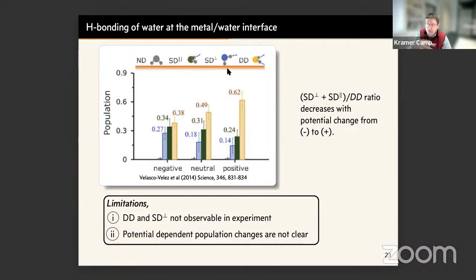What you find if you now compare experiment and theory is the picture shown here, right? As you go from negative to neutral to positive with respect to the potential of zero charge, the amount of the single donating species decreases with this potential change. And this is at least consistent in approximate terms with this textbook picture of changing water orientation. But of course, from our point of view, it's kind of insufficient, right?